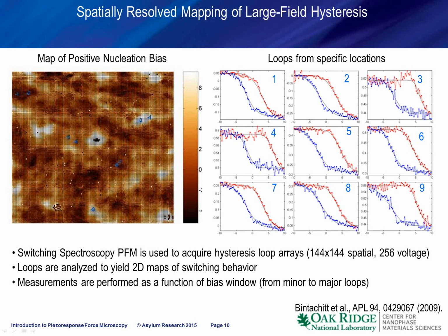hysteresis loop on the ferroelectric capacitor when we acquire a large 144 by 144 map of the hysteresis loops, and we can visualize the polarization switching at different locations. So analysis in this case is obviously much more complicated because when we do switching on the bare surface, we nucleate the domain only below the tip. In capacitor, the domain can nucleate anywhere, and we detect it only when it moves under the tip.